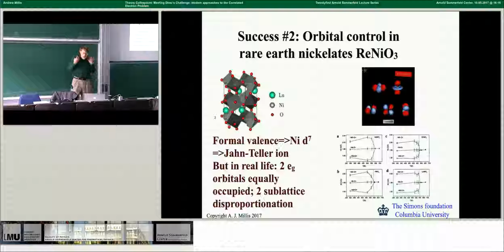Now, in cubic symmetry, these 2 orbitals have a twofold degeneracy, and they have a shape. So the Jahn-Teller physics says that the system would like to lift this degeneracy, make a lattice distortion that either makes a short bond in the z direction if you pick this one, or a long bond in the z direction if you pick that one, and lifts the orbital degeneracy. So you pick one of these 2 things, you lower it, and you make a lattice distortion to match. That's the naive thing you would expect. In fact, what happens is the 2 orbitals are equally occupied, and you get this 2 sublattice disproportionation.